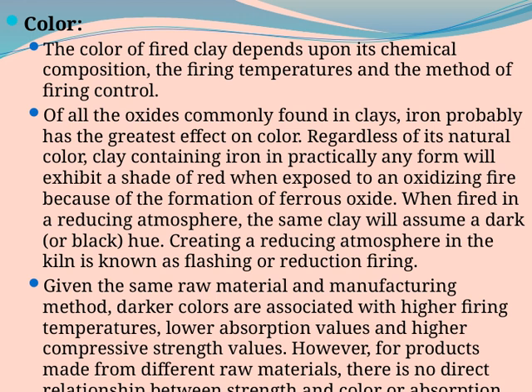However, if we fire the same clay in a reducing atmosphere, what we call flashing or reduction firing, it will turn a much darker or even black color. This change in color is all about the atmosphere inside the kiln during firing. Another important point is that darker colors are generally associated with higher firing temperatures. When clay is fired hotter, it tends to have lower absorption values and higher compressive strength. But, and this is key, if you're working with different raw materials, there's no straightforward relationship between color and strength or absorption. So, in essence, color gives us clues, but it's not the whole story when it comes to the properties of fired clay.